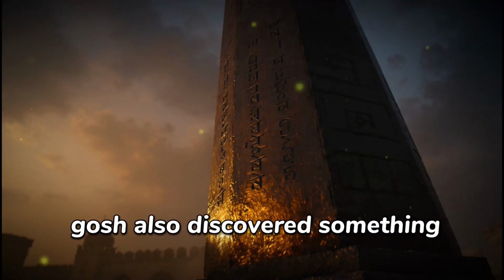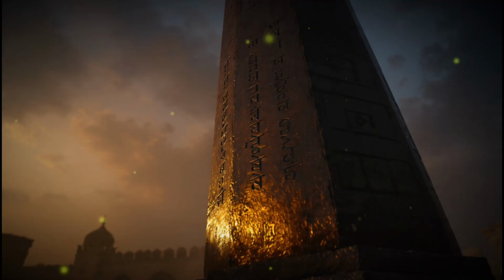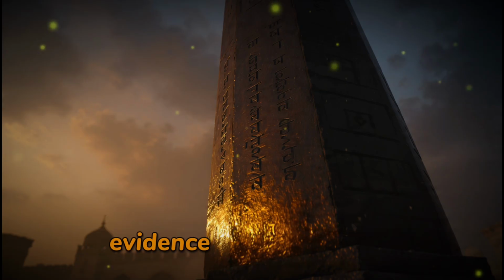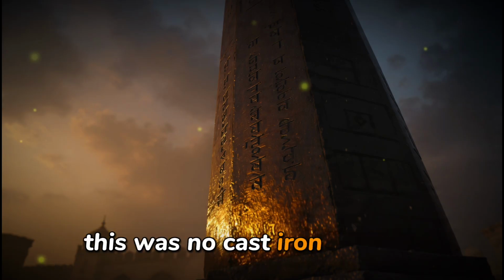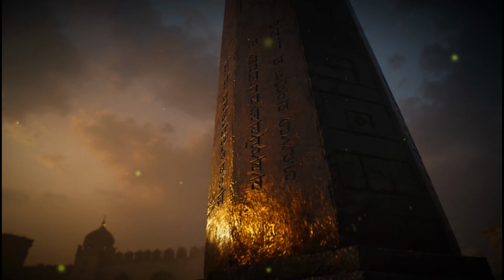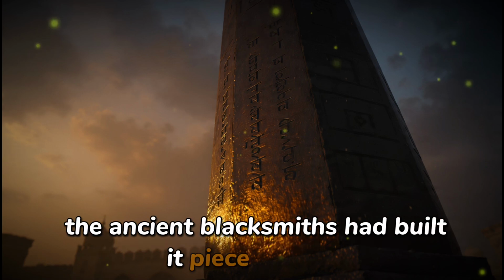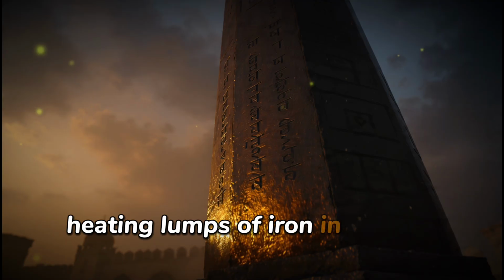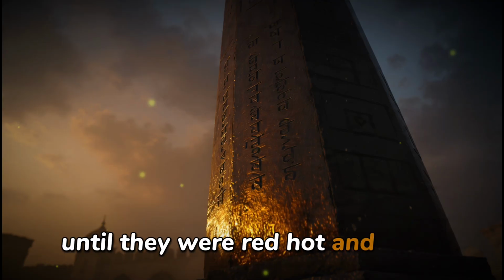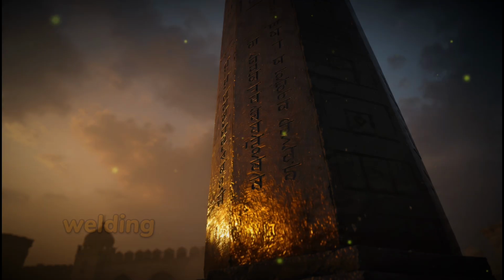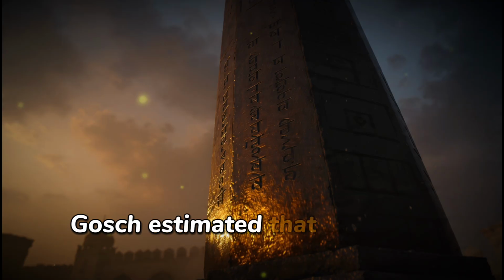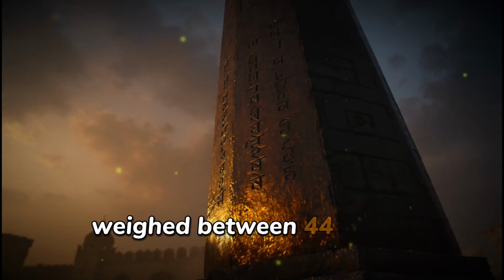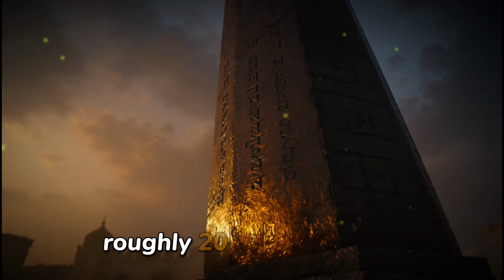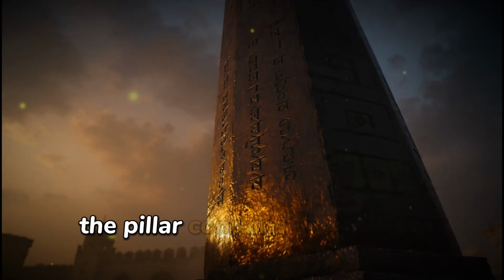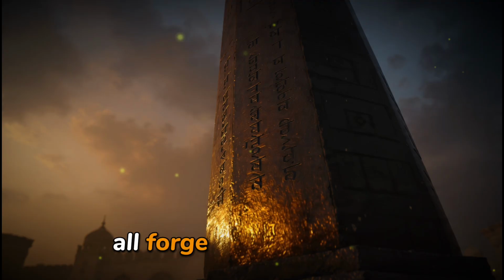Ghosh also discovered something remarkable about how the pillar was constructed. The surface showed hammer marks, evidence of forge welding. This was no cast iron structure poured molten into a mould. Instead, the ancient blacksmiths had built it piece by piece, heating lumps of iron in charcoal furnaces until they were red hot and plastic, then hammering them together, welding them through sheer force and heat into a unified whole. Ghosh estimated that each lump of iron weighed between 44 and 66 pounds, roughly 20 to 30 kilograms. The pillar contains hundreds of these pieces, all forge welded together.